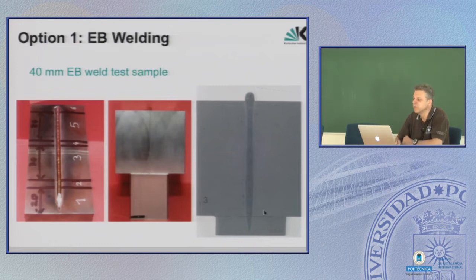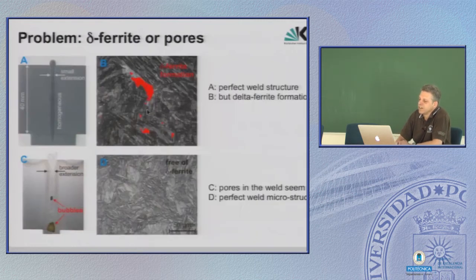It is narrow, it is deep, looks quite homogeneous without any defects, and so we thought, well, it was easy peasy, no problem. But there's almost always a but. If you examine the weld in more detail, then you see that there are some phases which don't belong in Eurofer. And now you have to remember yesterday's formation of delta ferrite. Delta ferrite is a phase at very high temperature near the melting point, and especially during welding with rapid cooling there is a leftover of such ferrite formations which do not transform into martensitic structures. So these red dots here are all delta ferrite. Compared to martensite, delta ferrite is very, very soft, and this means you have many very soft spots in the weld line, and this causes problems later on.